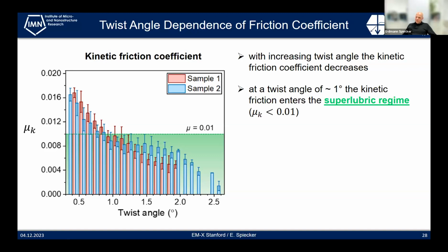So not each twist angle is, of course, incommensurate. But like with grain boundaries, you have certain coincidence site lattices, and then one would expect to see an increase of friction force. But I would expect that this is very difficult to reveal experimentally, these kinds of plots of friction as a function of twist angle, because you cannot fully control it, because the whole system is not stiff. You cannot say, I make a twist angle and just pull on it and look for the friction force, because the system reacts to your forces and may twist or may not twist depending on what is energetically favorable. And we also saw this gradient of twist angle from bottom to top, which you cannot avoid, but we could even exploit it to have more data for different twist angles.